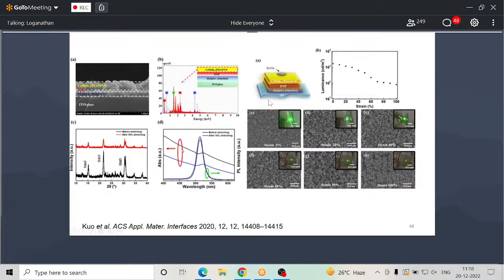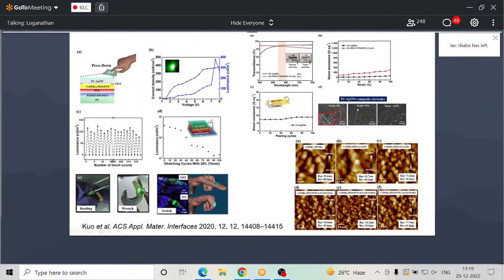Here we can see their performance and their energy output. Here we can see the cross section. From that we are able to say that even after 50% straining the LED, the crystal characteristics of the perovskite still remain the same. So here we can see the FESEM, here 0%. The LED luminescence is like this, but if you strain them to 20, 40 like that, the luminescence will quench a little. So here we can see the performance up to 100% strain. It's relatively stable, so it's good for real-time application.